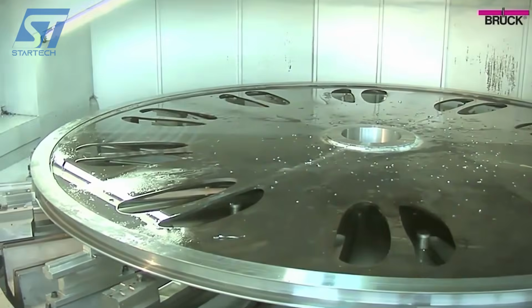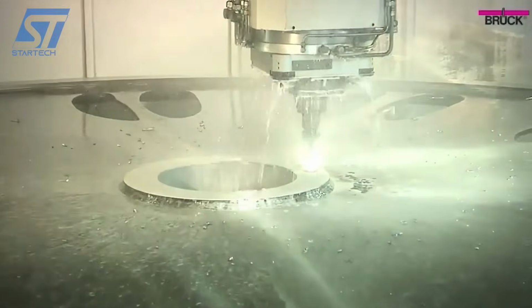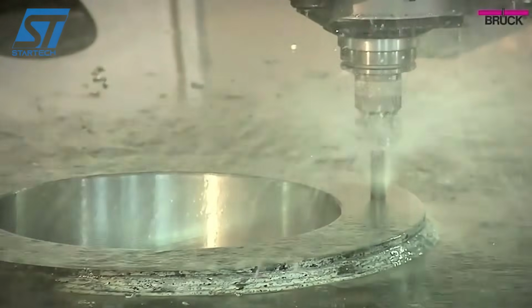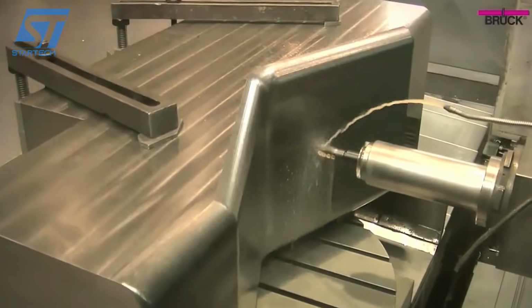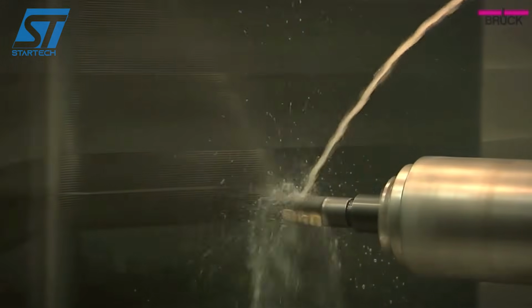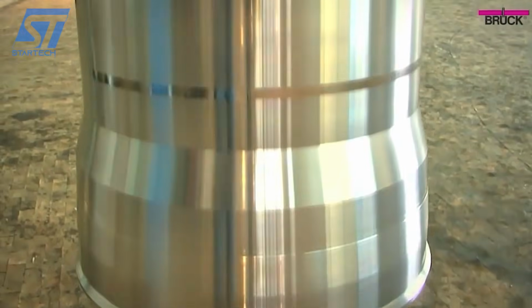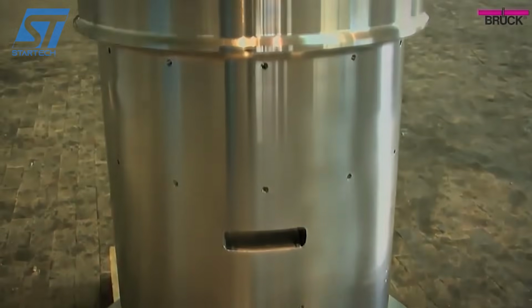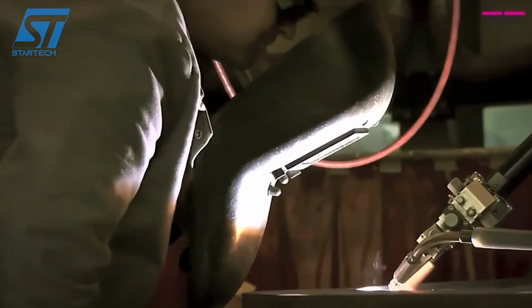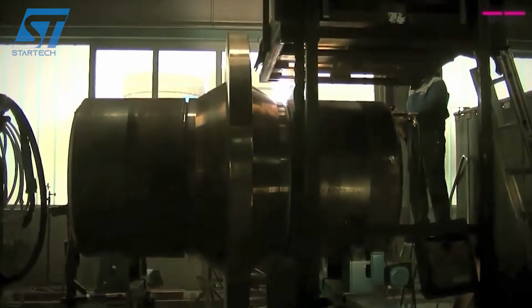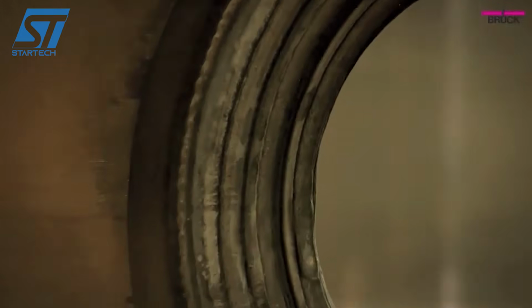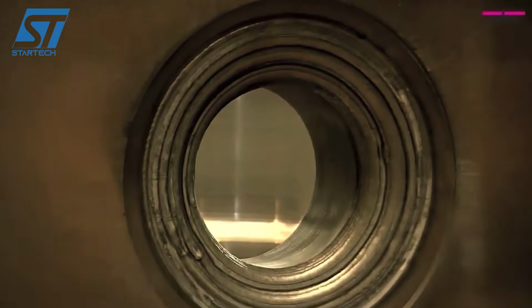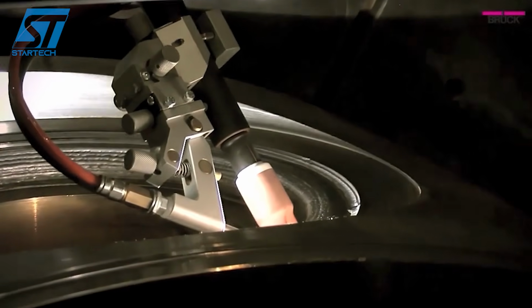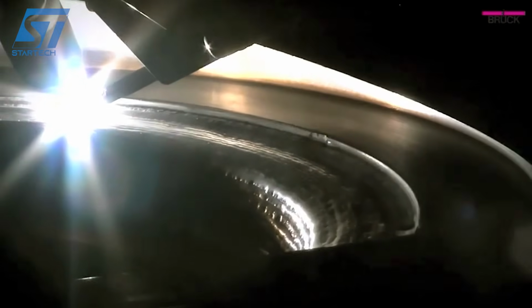Bruck's machines use radial axial ring rolling, which means they're controlling the shape both radially, the wall thickness, and axially, the ring's height, simultaneously. This gives engineers extraordinary control over dimensional accuracy and grain structure. And that grain structure is the key technical advantage here. In a seamless forged ring, the metal's crystalline grain flows continuously around the circumference, following the ring's shape. Compare that to a ring cut from plate, where the grain runs in straight lines and intersects the ring wall at awkward angles. A forged ring is fundamentally stronger.